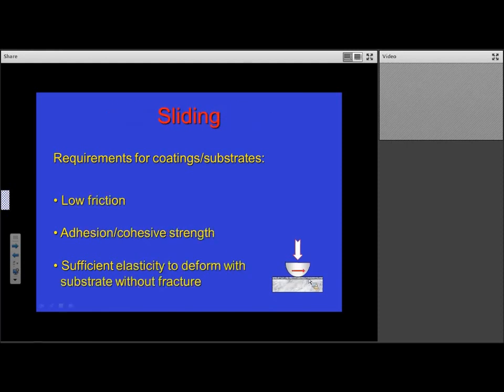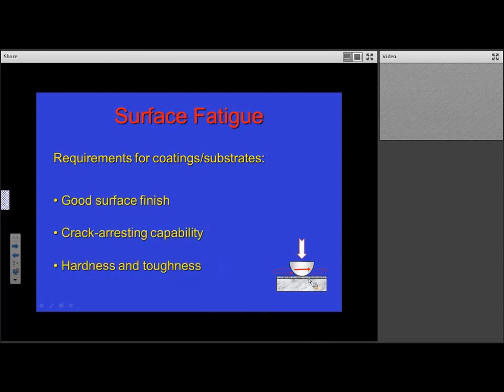For a sliding contact, you probably need low friction. You need sufficient adhesive strength between the coating and the substrate, and you need adequate cohesive strength within the coating and within the substrate as well. And you need sufficient elasticity in the coating to deform with the substrate without fracture. For a fatigue situation, normally you need good surface finish, you need a crack arresting capability, you need adequate hardness and toughness as well. So although hardness comes into many of these requirements, it is by no means the only requirement that they have.